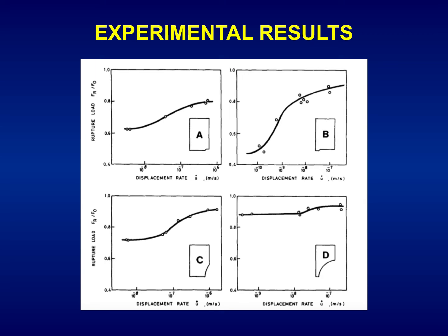Then we don't have a more damaging effect of hydrogen for decreasing displacement rate. We have reached the equilibrium condition for hydrogen-metal equilibrium in the metallic lattice, and then we have the quasi-static test asymptotic left-hand side value.